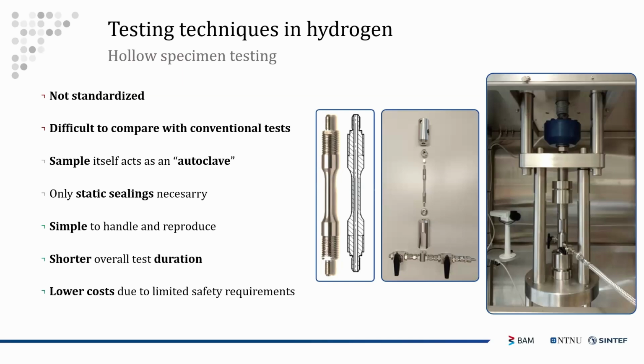But in this case, as it was mentioned before, the sample itself acts as an autoclave and mimics the conditions of a pipeline or a tank. In this case, only static sealings are necessary to isolate the specimen. And therefore, this technique is way simpler to handle and reproduce compared to autoclave testing. It has a shorter overall test duration and very limited costs. I cannot go in depth on this point, but there is an order of magnitude of difference in costs for each test. So it is extremely noticeable.